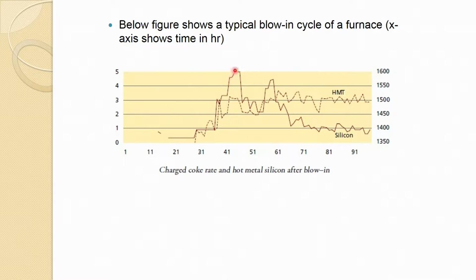So, there you can say probably the first casting of the slag, which is appearing here, and because you are now starting the ore to coke ratio in increased form, slowly this ratio is coming down, and finally it reaches its normal silicon content, less than 1%. So, that is where normal operation is resumed, and even your hot metal temperature is getting stabilized here. So, this shows almost 3 to 4 days minimum is taken to get the normal operation of the blast furnace after blow-in.